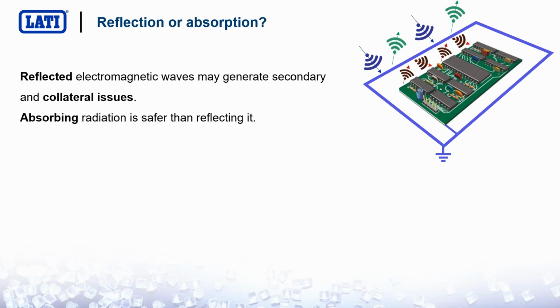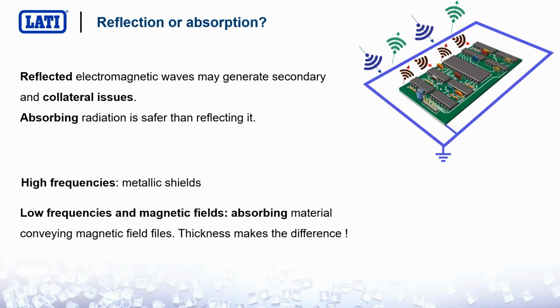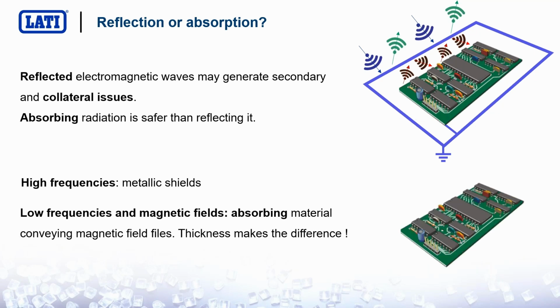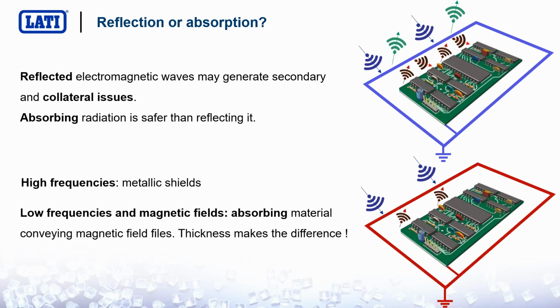It is better to have a solution that can actually absorb it, especially when it comes to low frequency and magnetic fields. For this reason, we are now developing materials which are capable of not only reflecting, but also absorbing the magnetic field. If we have a solution that absorbs the magnetic field, both incoming from outside or generated from inside, the radiation will be easily conveyed on the shield and then grounded. And this is, in our opinion, the best way to deal with electromagnetic shielding, no longer reflecting, but actually absorbing it.